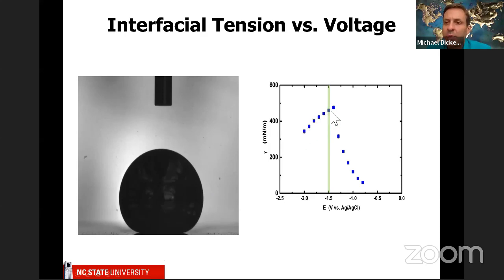This is exactly what you would expect from theory from the late 1800s, but something weird happens right here. And it turns out right here where we get this anomalous behavior, this huge drop in tension, that's exactly where the oxide first starts forming. And in fact, the tension gets lower and lower and lower. And I like to joke that when you see this data, you should be very mad at me because somehow I let my student graduate without taking one more data point. And gosh, wouldn't that be amazing if liquid metal, the liquid with the highest tension known to man, could reach zero interfacial tension using only 1 volt. So this is not electrowetting, this is not electrocapillarity, this is something different, and it has to do with surface oxidation.